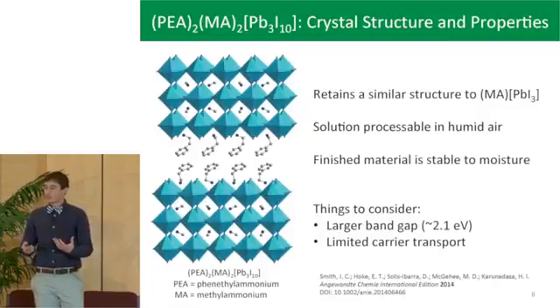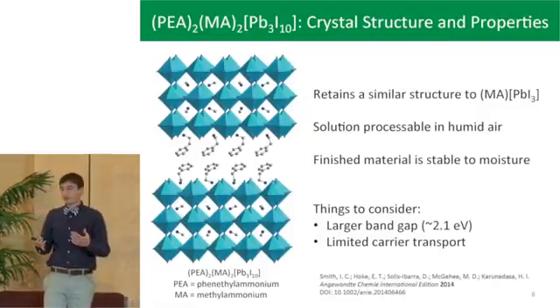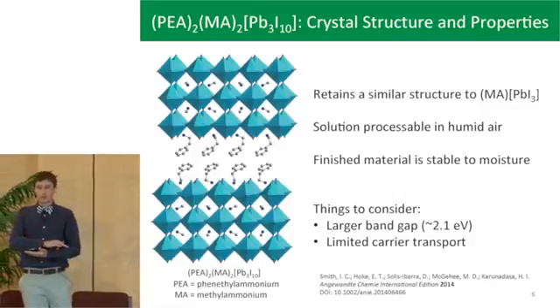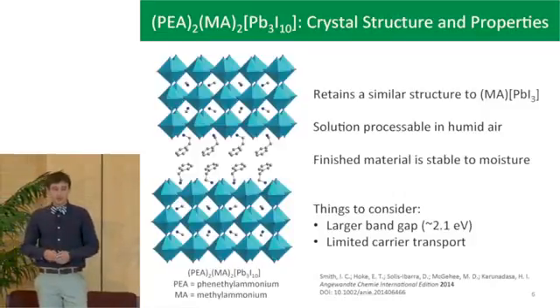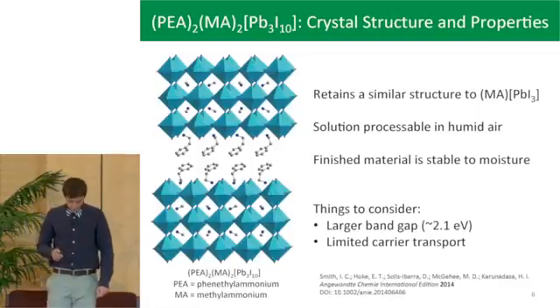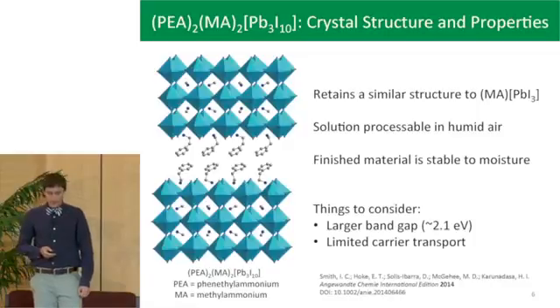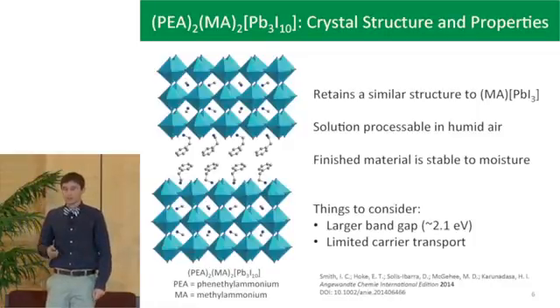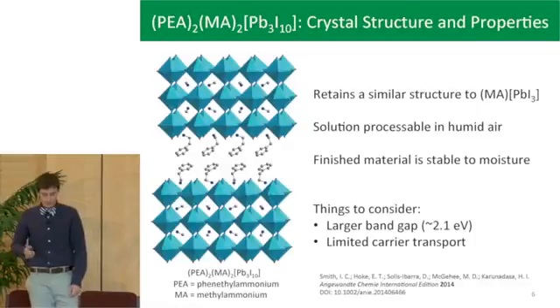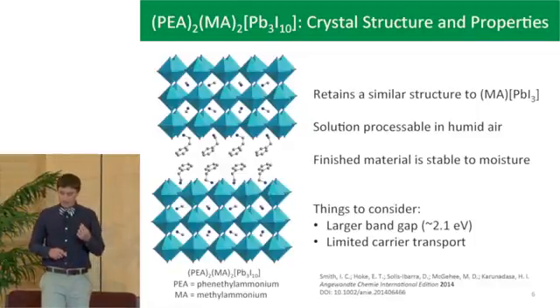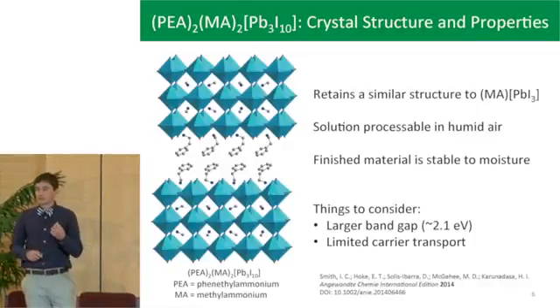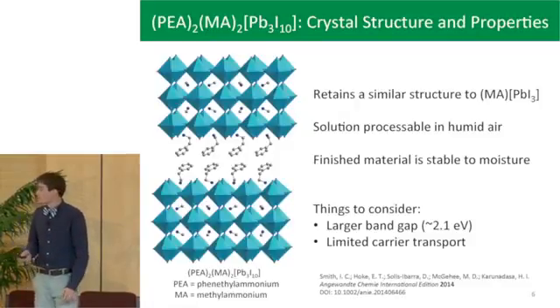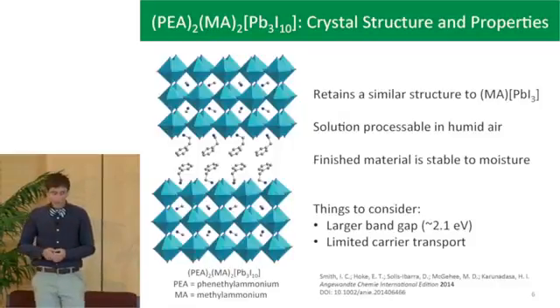However, in this case, it's actually easier to make films out of this material, both because of the layered structure, allowing you to spin the material down on a substrate more easily, but also because you can do it in ambient conditions, which is nice. And after you make the film, it is also more stable to moisture than three-dimensional material, and I'll talk about that later on. But some things to consider, like I said, these layered materials have larger band gaps, which means you're absorbing less of the spectrum. We think this material might actually be better for a tandem device.